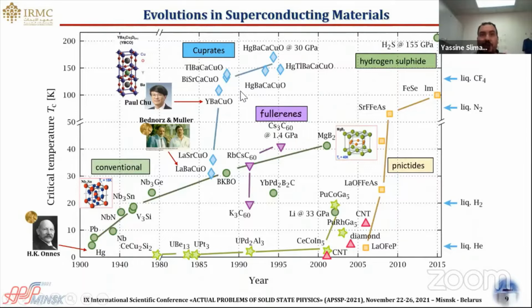So the well-known cuprate superconductors are the YBCO with a critical transition about 92 Kelvin, and the BISCO with a critical transition temperature around 110 Kelvin. As is clear here, these materials display a critical transition temperature above the temperature of liquid nitrogen, so they are classified as high temperature superconductors.